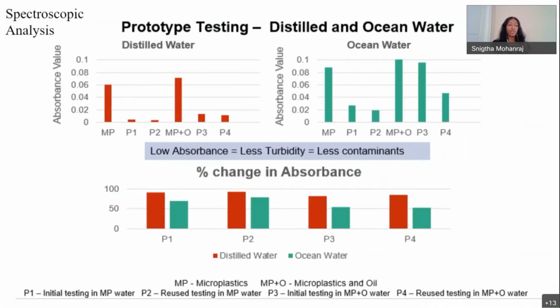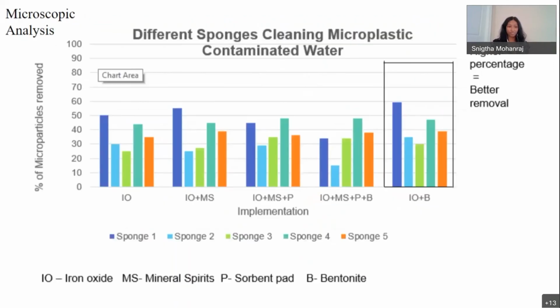So then I went to the third round of testing where I developed my final prototype, the iron oxide and bentonite coated sponge, which was created by using a polyurethane sponge, which was the material of sponge 1. And this was used to treat both distilled and natural ocean water. And in both instances, it successfully removed most of the contaminants.